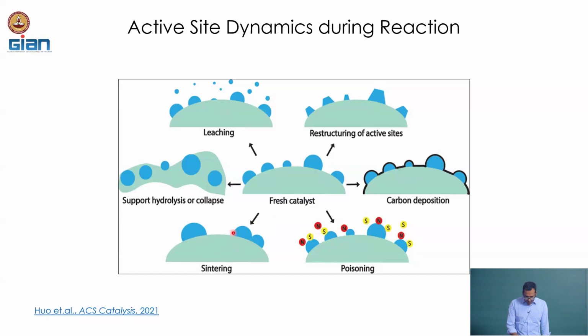It can happen that sintering is taking place, for which we will see an example in the next slide, where some of the smaller particles come together to form a bigger particle. We can have support hydrolysis or collapse, where the support oxide structure changes from one phase to another, or its surface area collapses over time on stream. We can have different kinds of poisoning. We can have carbon deposits on the active material such that the access of the gas to the active material is restricted, which can cause deactivation of the catalyst. Or we can have side products or impurities in the gas stream which have a much higher affinity to stay on the active surface, such that they hinder the access of the actual reactant to the active surface, which is typically known as poisoning.